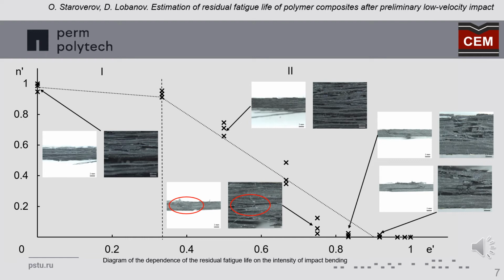Analysis of the diagram of the change in the residual fatigue life made it possible to reveal the presence of a shock sensitivity threshold. Impact loads with energies exceeding the threshold value lead to a significant decrease in fatigue life, by more than 10% of the nominal value of the maximum number of cycles, for the studied carbon fiber composites.